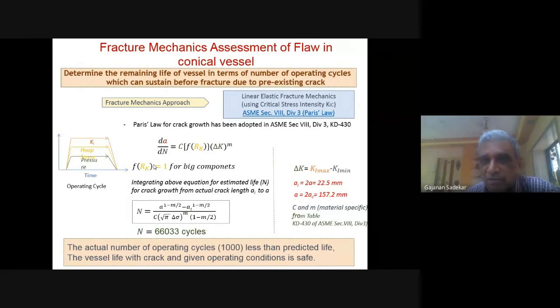At the end of the day, we calculated the cycles it will withstand, to determine the remaining life of the equipment, and we found the cycles it can undergo is 66,000, whereas the actual operating cycles were only 1,000. So we said in this case there is no way it will fail. I want to tell you something: we guaranteed the plant that don't worry, this equipment will never fail. And this is approximately now 14 years, not 14, it's more than that, 16 years, the equipment is working.